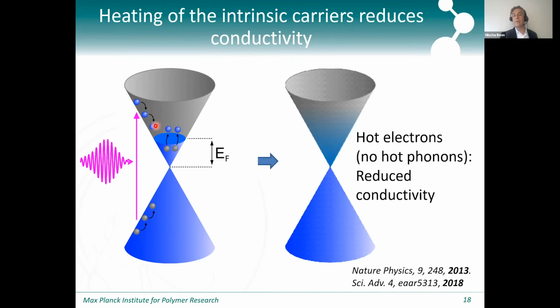And what that means is that the Fermi-Dirac distribution of carriers will essentially heat up, and as with conventional semiconductors, what happens is that the hot electron population has a lower conductivity than the cold electron distribution. And so in that sense, the graphene really behaves like a metal: when you heat it up, it is less conductive. And so this sounds a posteriori very trivial, but at the time that we found it, it wasn't.